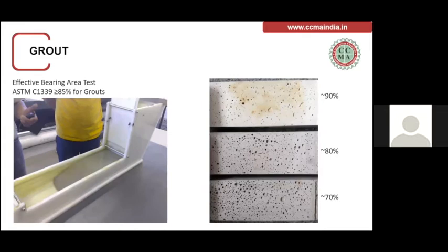Effective bearing area is one of the important aspects, because in case the contact surface area is poor, if the grout which is used to fill the joint connections has less contact surface area, there are very high chances that the grout would fail, like the load transfer would not be proper. So ASTM C1339 suggests that the minimum effective bearing area should be greater than 85%. In case it is less, there are chances the load transfer would not be proper between the grouts. So this is another important test which can be done at site.